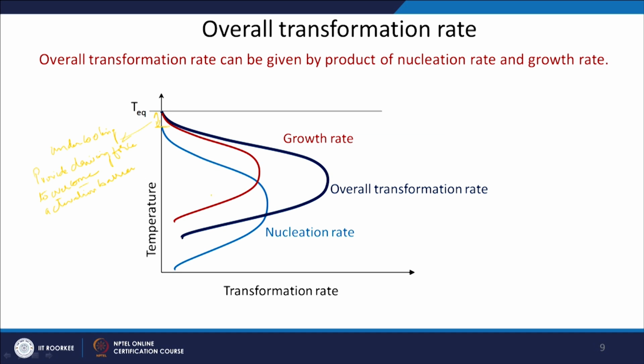If you combine both the nucleation and growth, you will have an overall transformation rate. As a function of temperature, as you bring down the temperature, the transformation rate will increase, become maximum at some intermediate temperature, and then start decreasing as you bring down the temperature. So, this is the overall transformation rate, combining both the nucleation rate and the growth rate, to show how the transformation rate will change as a function of temperature.